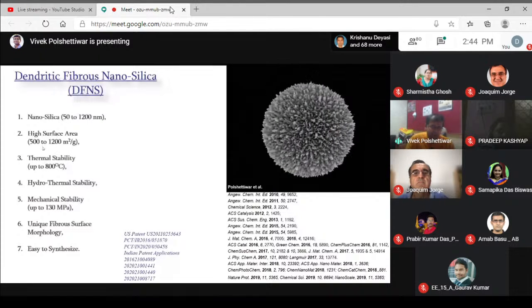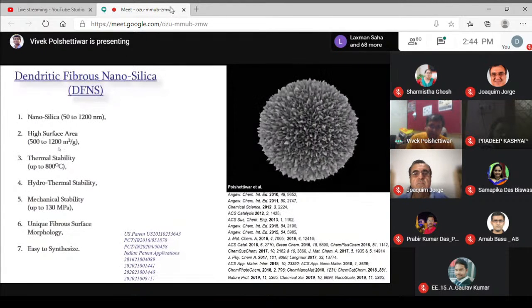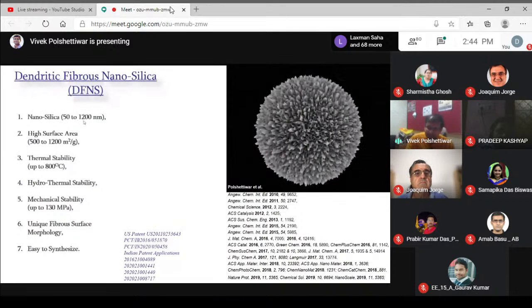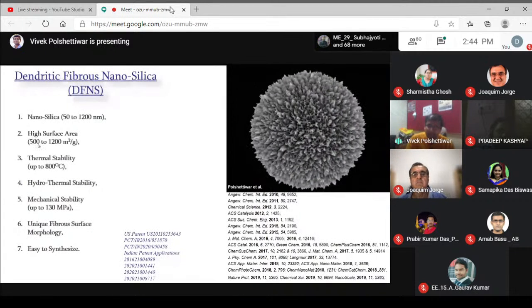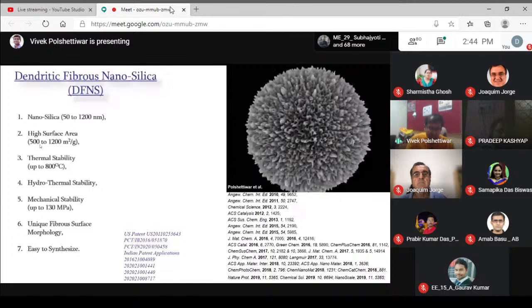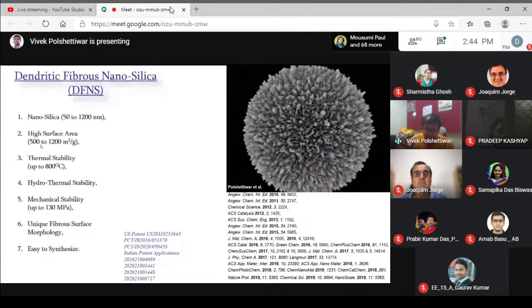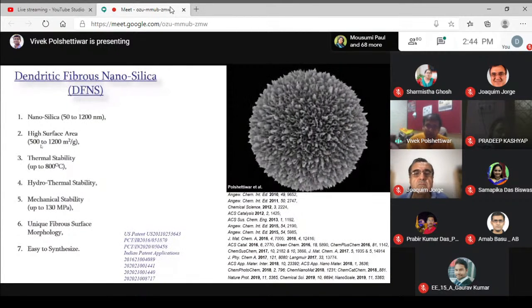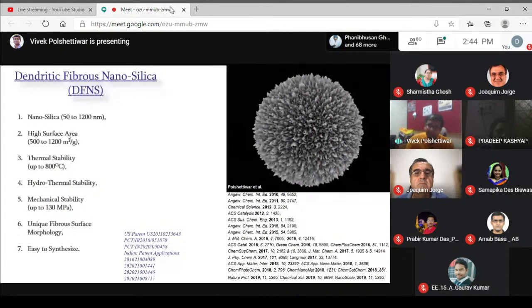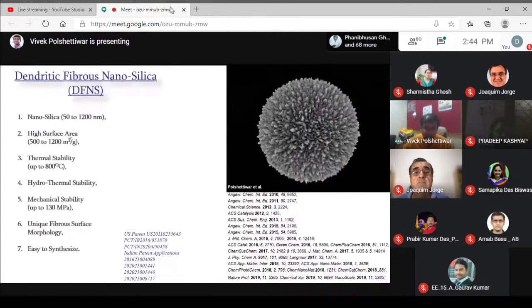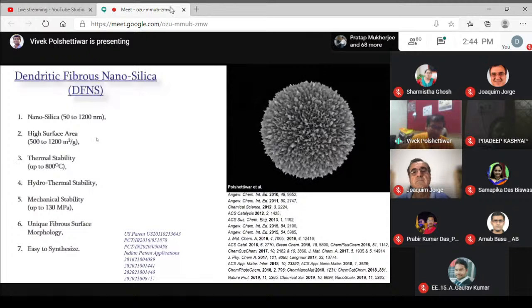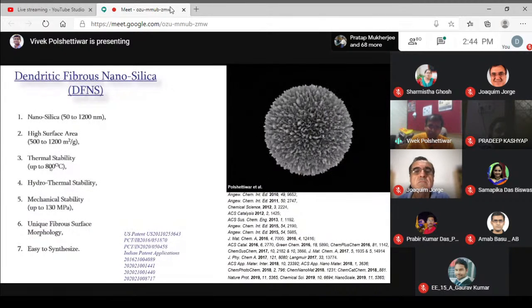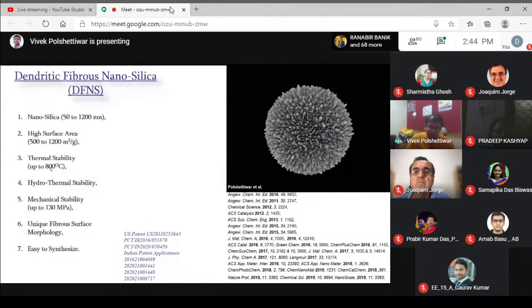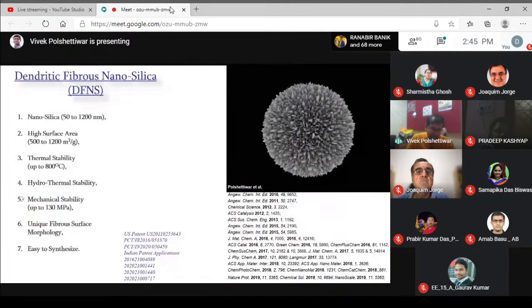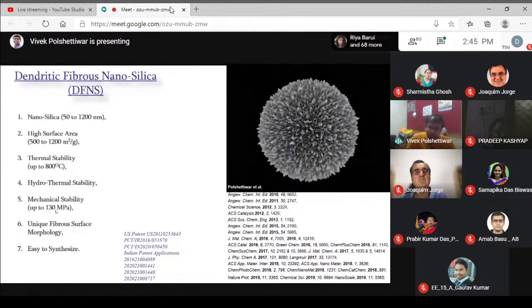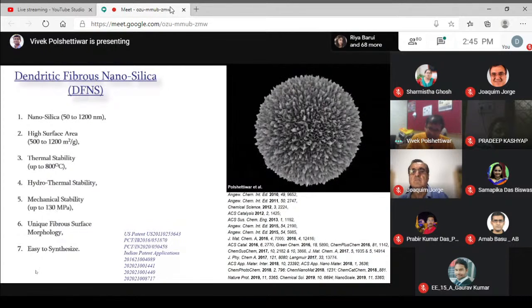Surface area is also very high, from 500 to 1200 meters squared per gram. For example, if I prepare a nanosilica of 600 nanometer, the surface area is around 500 meters squared per gram. What is this? It's like if you take 1 gram of a powder in your hand, it's like 1 football ground in your hand. So that's the huge surface area that can be used for different applications in addition to catalysis. Excellent thermal stability, so you can heat them up to 800 degrees Celsius, or do any processes which need 800 degrees Celsius. Stable up to 130 MPa, so one can do processes which need high pressure, and it's easy to synthesize.